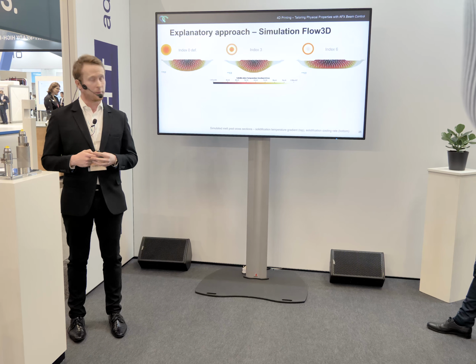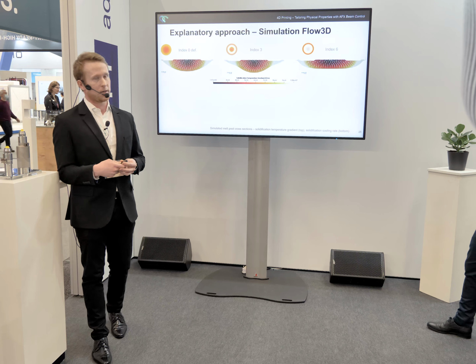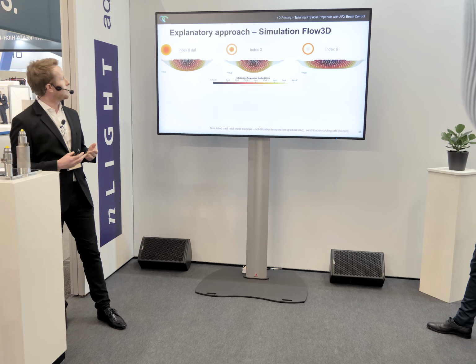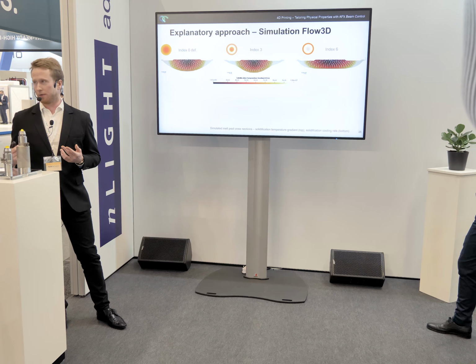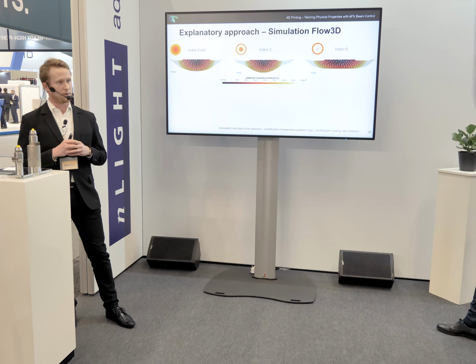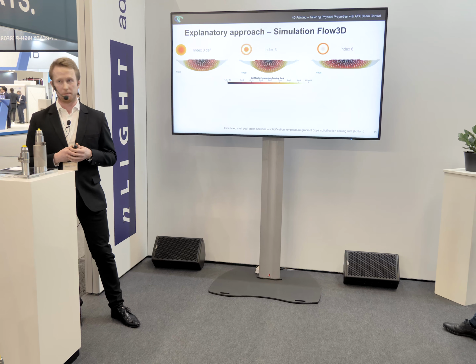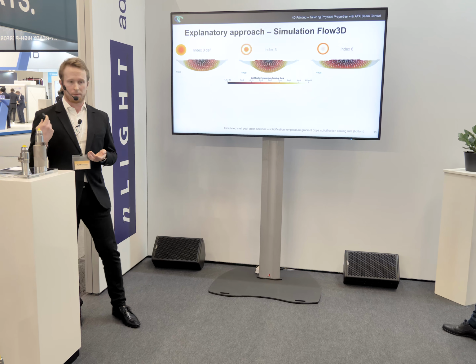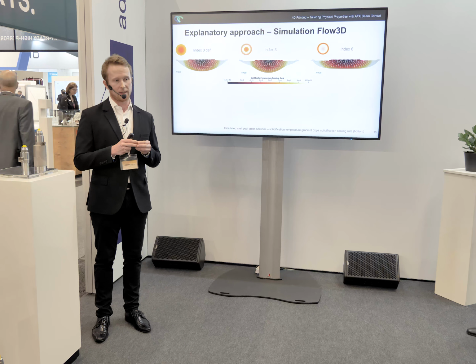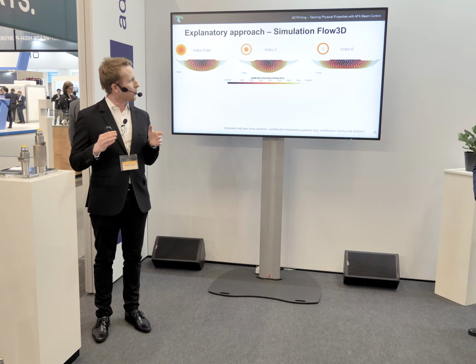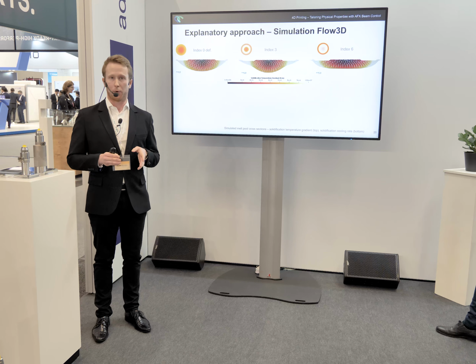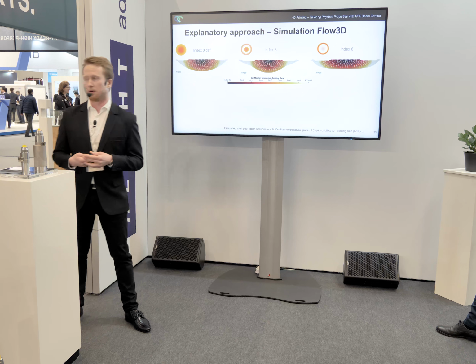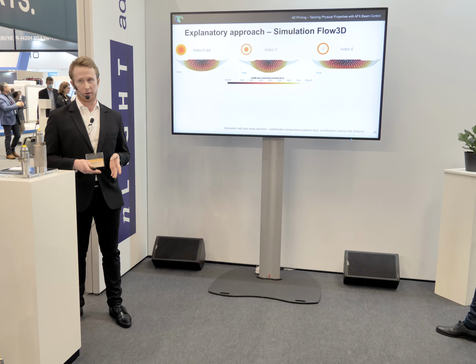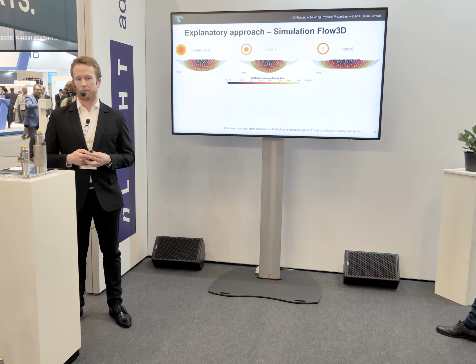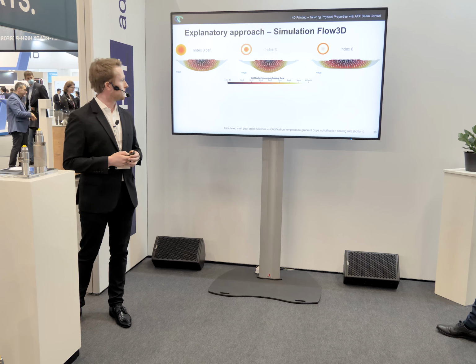Next, we look deeper into what actually happens in the melt pool. One of the useful pieces of information that we can get out of the simulation is the solidification temperature gradient. What we can see here is that the solidification temperature gradient vectors are all pointing towards the center of the melt pool, which is the center of the laser beam. And by the pure fact of making the melt pool shape wider and shallower, more of them start to be parallel to each other and point in the Z direction, which would be one of the indicators of where the parallel dendrite growth in this process comes from, which corresponds to the increased mechanical properties.